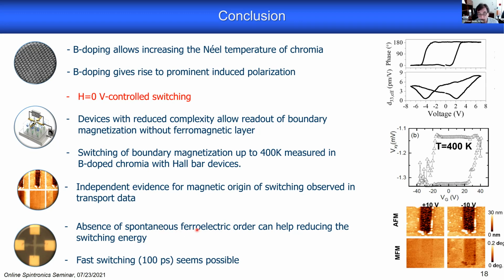It's also worth mentioning that this system is not a multiferroic system, and the absence of spontaneous ferroelectric polarization can be considered positive, because in systems such as BFO, for example, where you have ferroelectric order, it is the ferroelectric order and the hysteresis that comes with inversion of the polarization that is detrimental to energy and speed.